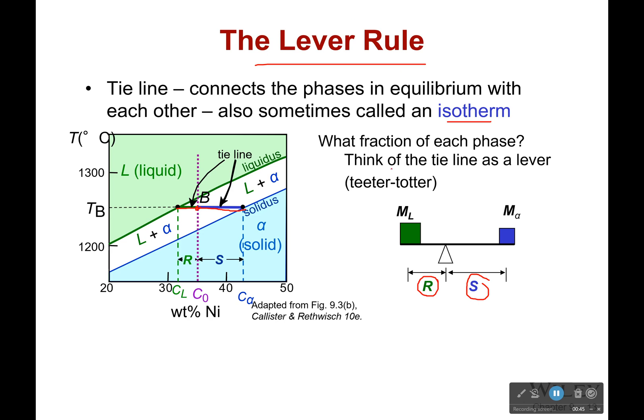And we're using something called the lever rule which says that if I have a shorter lever arm, then I need a greater weight fraction to balance it out. Similarly, if I have a longer lever arm, then I need a smaller weight fraction to keep it balanced. So the shorter lever arm to my side, the larger my weight fraction needs to be to keep it in balance.